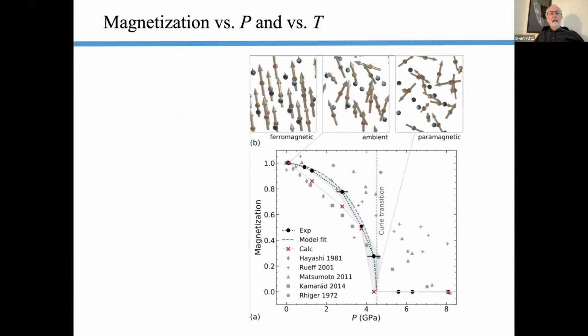So our theory colleagues did this as well, as I mentioned. They've looked at iron nickel in the spin-aligned ferromagnetic state, which is actually pretty much 0 Kelvin. Room temperature already has a fair amount of misalignment here in the spin orientations. The iron spins dominate. The nickel spins, these little blue ones here, are much smaller. And by the way, they tend to stay aligned a little bit better with temperature. So all the action is with the iron, which is great because we're doing iron 57 work.